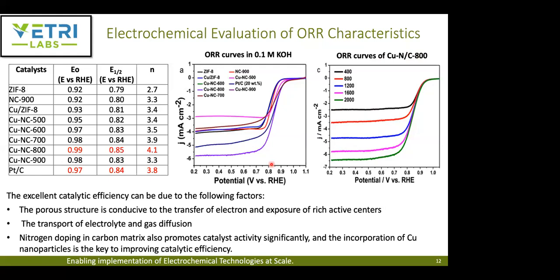And the catalytic activity of this copper nitrogen doped carbon at 800 degrees Celsius, they attribute to 3 factors. One is the porous structure, which is very conducive to the electron transfer, and it also exposes active centers for ORR. And also they help in the transport of electrolyte and gas diffusion with the presence of mesopores. And the nitrogen doping in the carbon matrix also promotes this catalyst activity. And the incorporation of these copper nanoparticles helps in improving the catalytic efficiency and also provides conductivity to this nitrogen doped carbon.